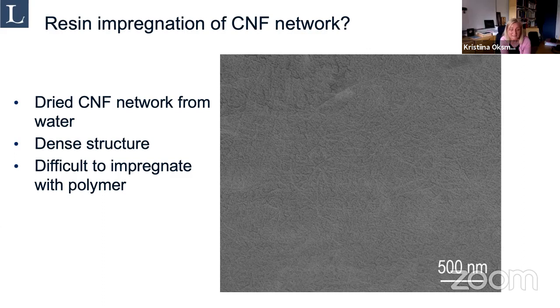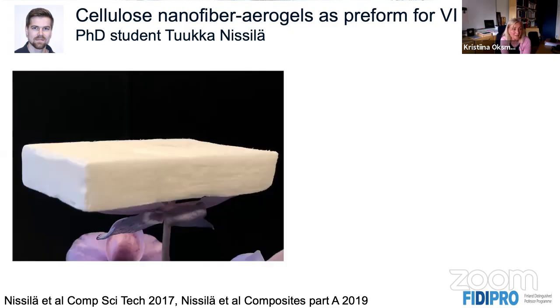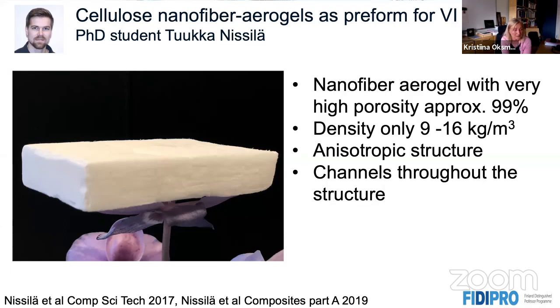So our interest has been to find a way how these nanofibers could be used in conventional resin infusion process. And for that, I have one PhD student, Tuukka Nissilä, who has been developing cellulose nanofiber aerogels as preform for vacuum infusion. And he has made extremely light materials from nanocelluloses. They have very high porosity, 99%. Density can be only 9 kilograms per cubic meter. And they also have a very anisotropic structure.